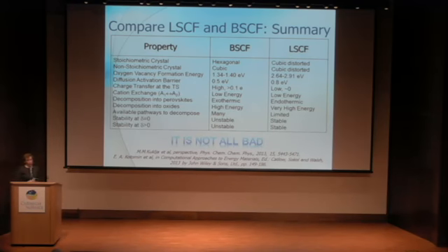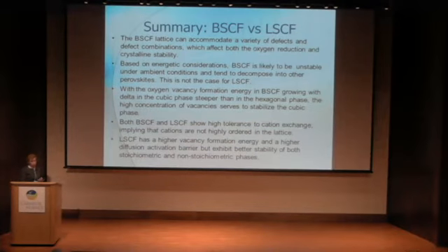Most important is that BSCF is unstable when it's stoichiometric or has high concentration of vacancies, and LSCF is much more stable than that. So we think that this will be actually a good alternative. Okay, and to summarize this, BSCF lattice can accommodate a variety of defects and defect combinations which affect both the oxygen reduction and crystalline stability. Based on energetic considerations, BSCF is likely to be unstable under ambient conditions and tend to decompose into other perovskites. And this is not the case with LSCF, which gives you a nice alternative for applications.